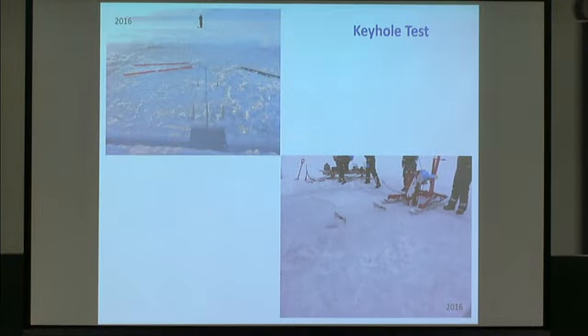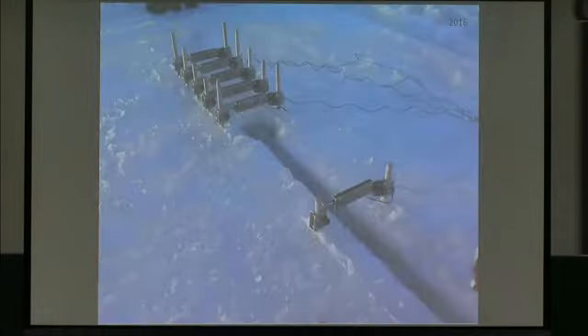Then, prior to starting the real testing, we made a notch here, not for the crack, but for the jack to go into here. A keyhole is made up here, and we were ready to do our first experiment. This is back in 2016, in order to see where we could expect the cracking. Where would we expect the c-axis to be, or the basal plane, and so on.